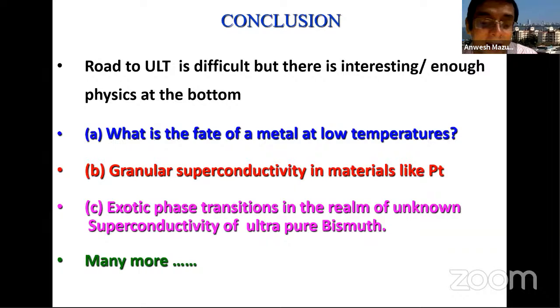Right. In the beginning, you said that with judicious choices of elements, we can make alloys that have higher TC. But how do we make such choices? Good question. This is a million-dollar question. When two elements are superconducting, you try to mix them, do a band structure calculation, and see what the criteria is which pushes the TC. If you believe BCS, then you have to make sure that the Debye temperature, which comes in the TC, is large.